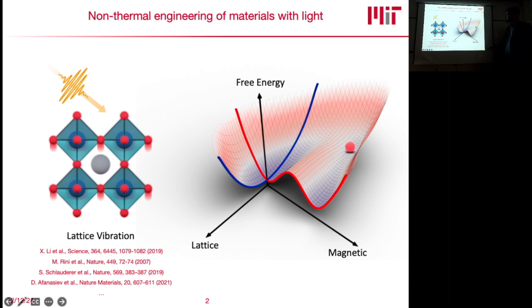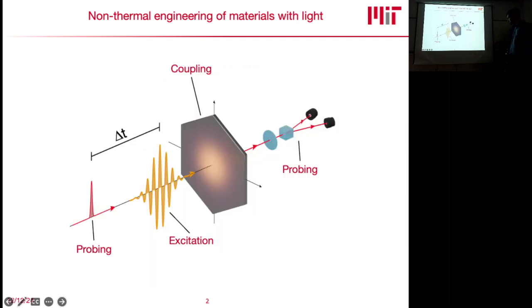And so this has been successfully done in the past, where people mostly use low energy light in the terahertz or mid-infrared region to collectively excite and coherently excite phonons in these materials. And this is usually dubbed nonlinear phononics. And so these types of experiments usually can be cast into three steps. So you need to be able to excite these collective modes, which is usually done with terahertz light. You need to be able to probe them ultrafast, so they have to have optical features that are characteristic of a certain state. And then this can be done with different types of optics behind the experiment.